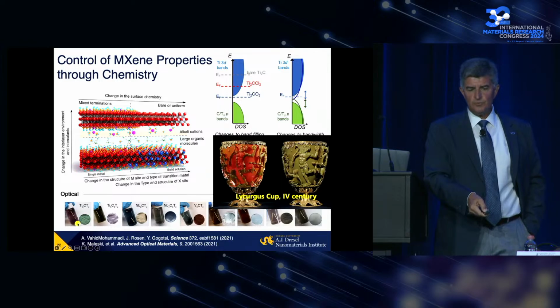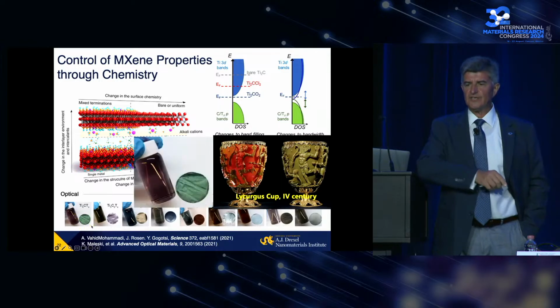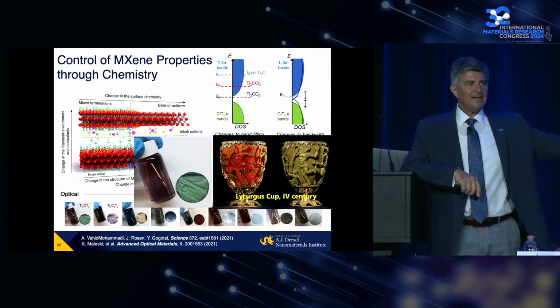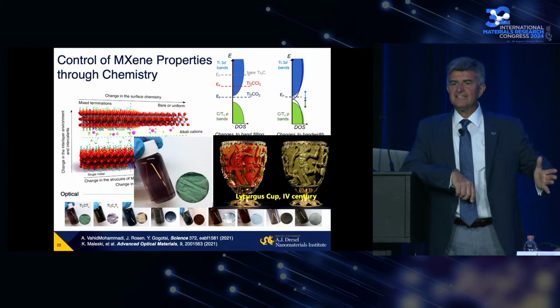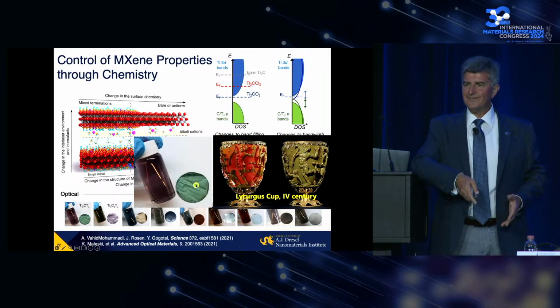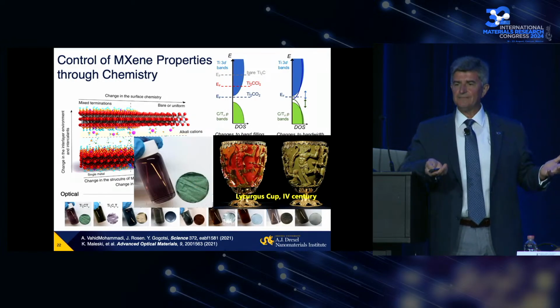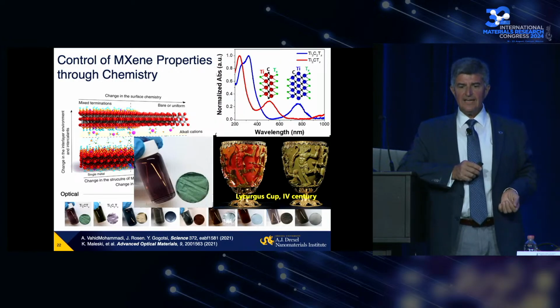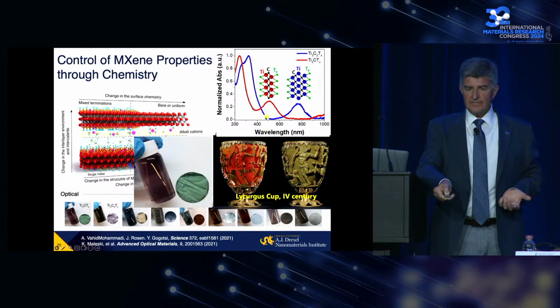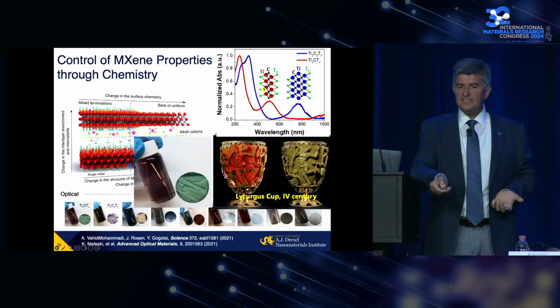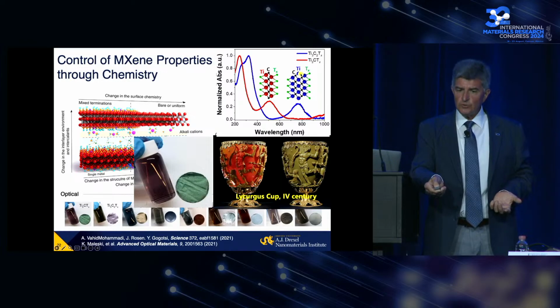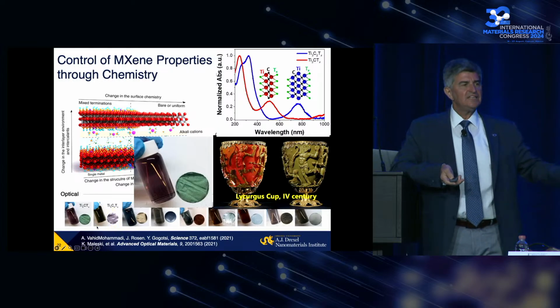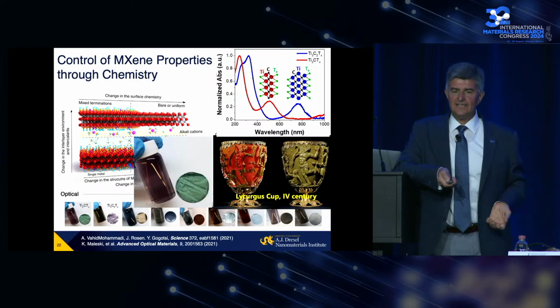Now look at titanium2C. It's red in transmission, green in reflection, and we can tune its properties electrochemically, making electrochromic materials in many other ways. The main difference is there's no gold here - just titanium, carbon, oxygen, some of the most common elements on Earth. There's a plasmon resonance peak at about 550 nanometers in titanium2C MXene. But if we add an extra layer of carbon and titanium to make titanium3C2 MXene, its peak shifts to about 780 nanometers, so it becomes green in solution and a kind of purple metallic in reflection. You can continue building with all the elements to get any color you need.